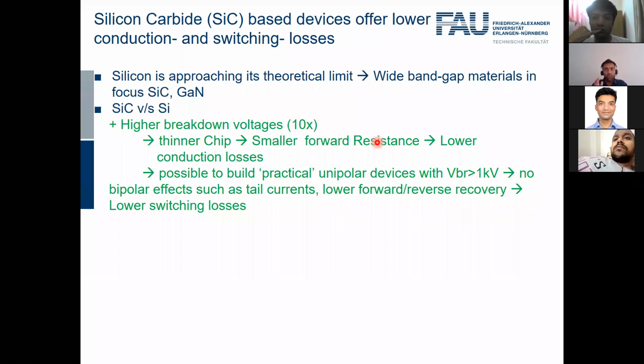But with silicon carbide, it becomes possible to build MOSFET devices or unipolar devices even in the kilovolt range. I have seen numerous publications where MOSFETs are built in the, let's say, 10 kV or 20 kV voltage range. And this is possible because silicon carbide has a 10 times higher breakdown voltage. So this means that we can realize practical unipolar devices also in the kilovolt range. So therefore, it's not anymore necessary to use only IGBTs, but we can also build silicon carbide MOSFETs in the high voltage range. So this is the main advantage of silicon carbide. How does this help us? I will explain in the next slide.